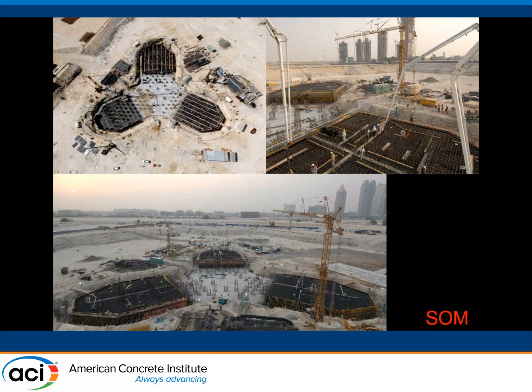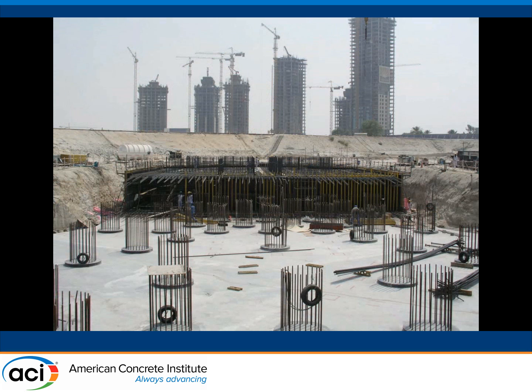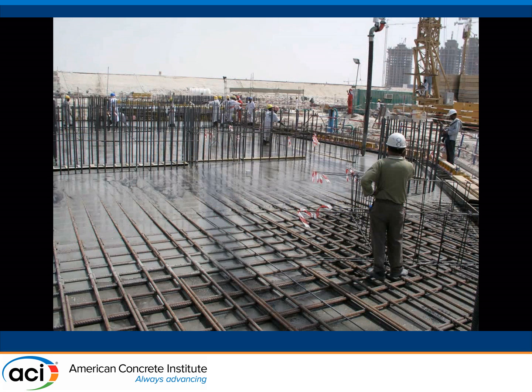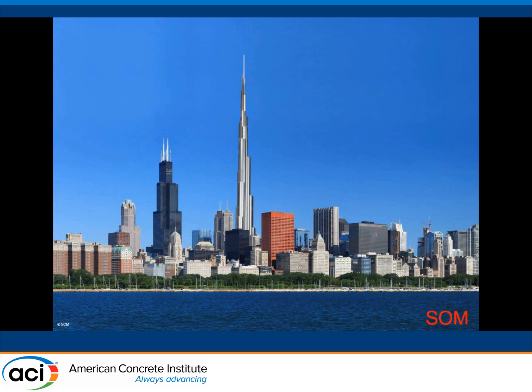And we poured this mat in 4 stages, each of the 3 wings, and then came back with the center portion to limit the amount of restraint that the mat created itself as it was drying and curing. Here's some images of the pile-supported mat foundation under construction. And then self-consolidating concrete basically filling up like a bathtub there. And I didn't have Kansas City, but I did put Burj Khalifa in the Chicago skyline, which is fairly close, and this is what it would look like.